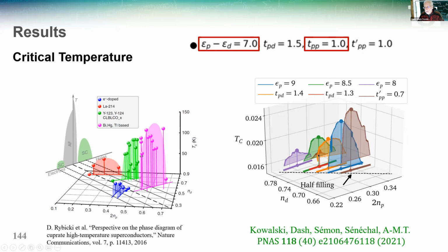Now, there are exceptions. For example, here, I don't know what happened with this set of parameters, but it's off. I should say that every one of these curves you have to think of as another material, so in other words, the parameters are different. We start from this base parameter set and we change them one at a time. The different colors represent a different material, and we move the chemical potential, or dope them, and we compute the TC. So we recover this correlation.